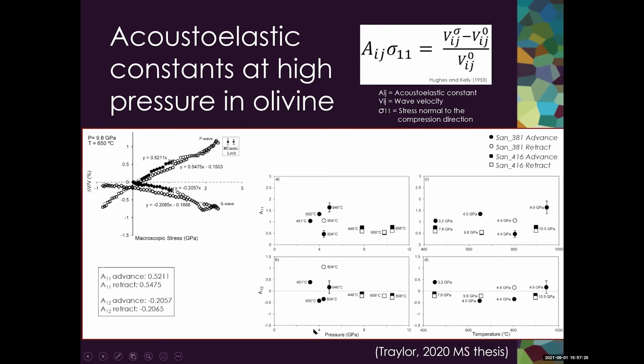On the right, we're plotting these acoustoelastic constants, the P wave A11 acoustoelastic constants and the shear wave A12 acoustoelastic constants, as a function of pressure and temperature for multiple deformation experiments that were done on San Carlos olivine. And what we see is that we observe a minor pressure dependence in the P wave data, and we're not really seeing much of a temperature dependence.